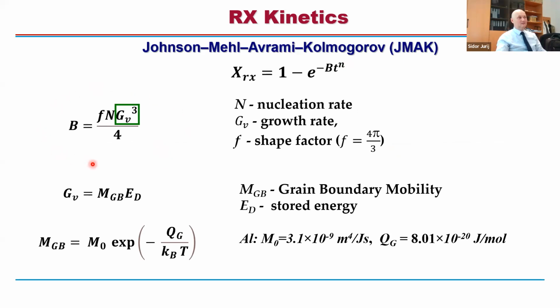Well, later on, scientists developed various techniques, and they managed to resolve a couple of problems. So it turned out that the B constant or B model parameter is a function of the so-called shape factor, which is a constant. Okay, then you have growth rate here and nucleation rate. And let's start with the growth rate. Growth rate is nothing else than the mobility of the grain boundary multiplied by the stored energy. Okay, I talked a lot about stored energy. At least we have quite reliable techniques to estimate the stored energy. And then the mobility you can calculate by this simple expression, right?